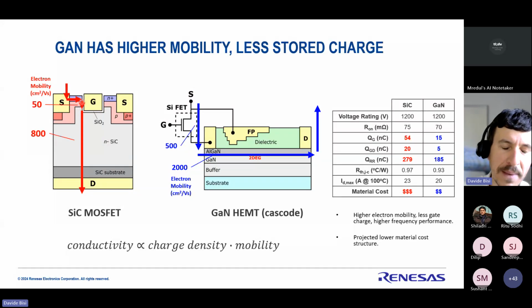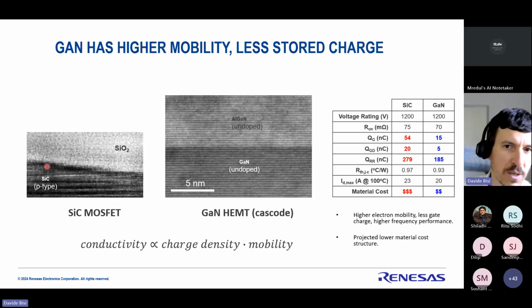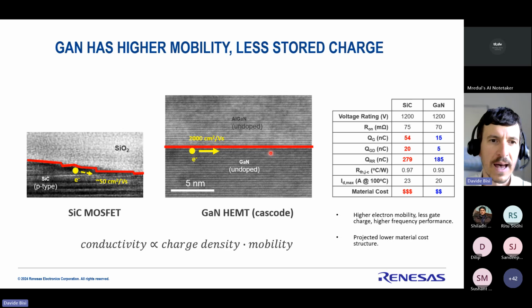If you look at the mobility of the silicon carbide device in the channel, where you have basically electrons flowing at a p-SiC oxide interface, mobility can be as low as 50 centimeters square per volt-second. Just to give you an idea, this is a TEM cross section of a silicon dioxide silicon carbide interface. You can see there are some bumps, and that's what makes mobility low in this channel, because electrons have to go through these bumps. Whereas on GaN, it's a very pristine interface, so electrons can zip at very high mobility through that interface.